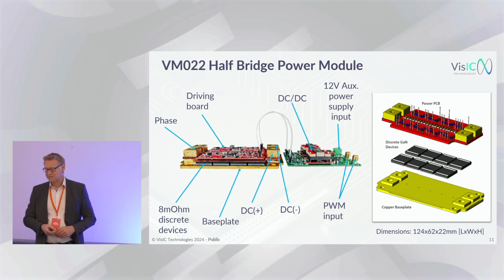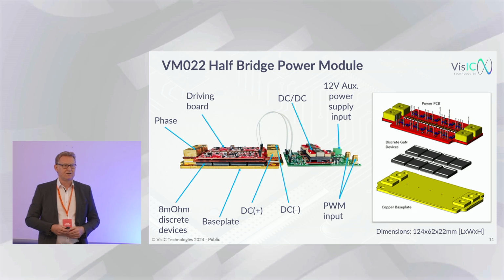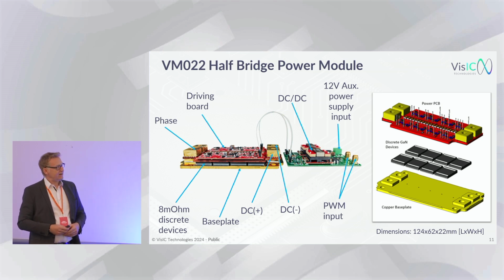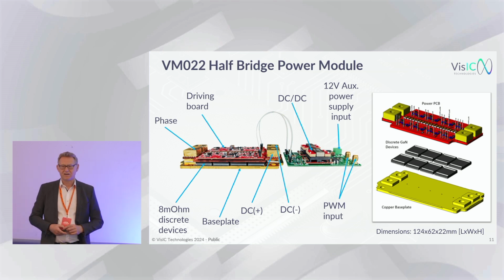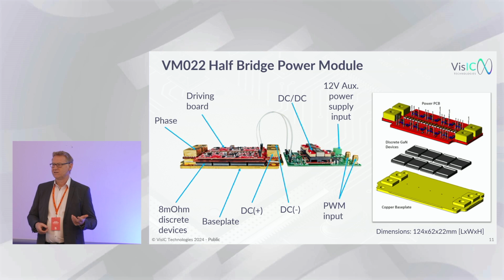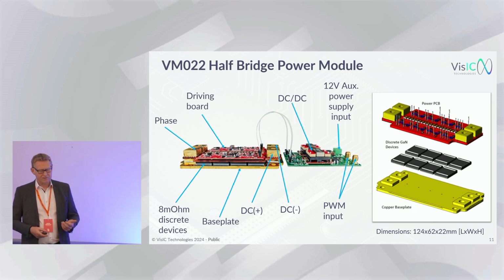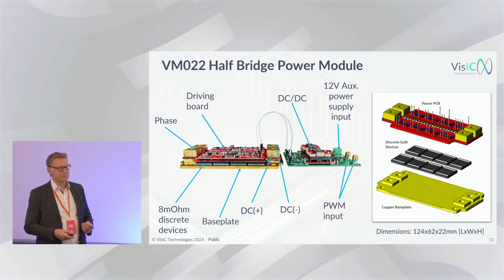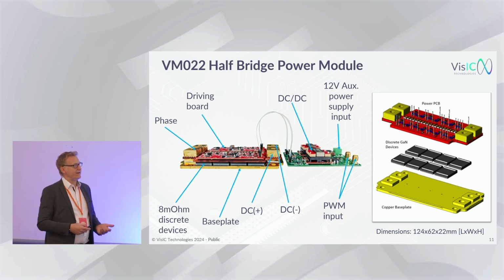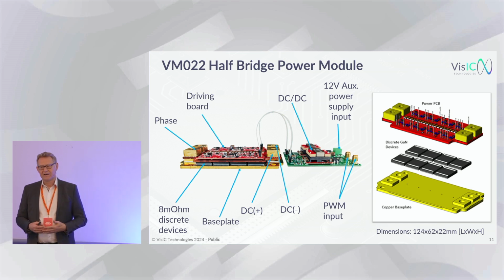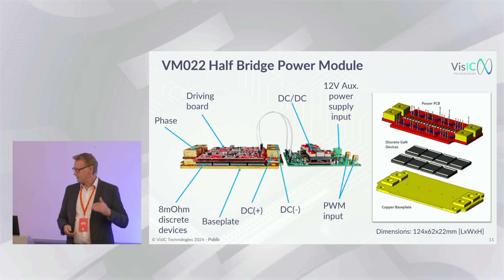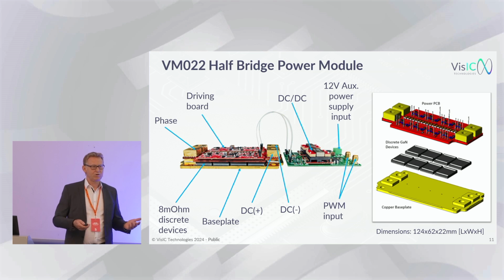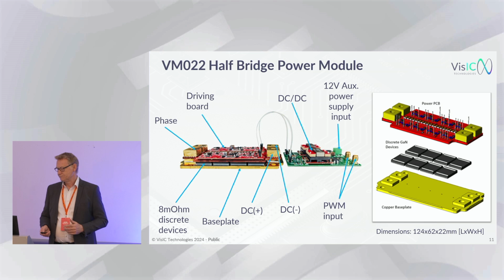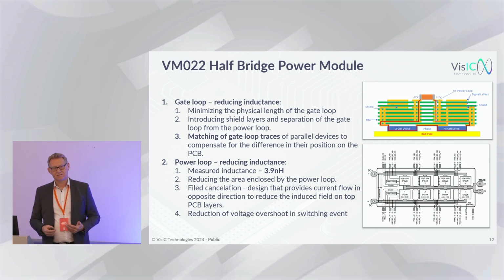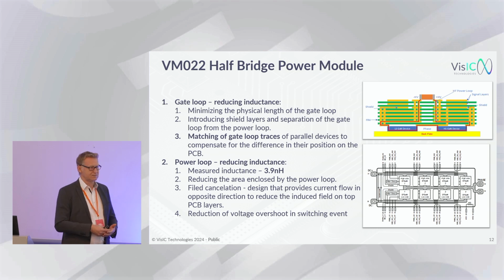So what we have done as a first iteration, in order to demonstrate the viability of the technology, looks like an Econodual from the outside, but it's not a real Econodual, because we are using our discrete devices, which use an aluminum nitride substrate inside, and we pre-pack them together with our gate driver board in order to have a very compact design, and then also put capacitors on it in order to make it very low inductance. So by achieving this kind of mounting technology, it looks like a power module. In reality, it's not a power module. But what it does is it reduces the capacitance and the inductance of the system.